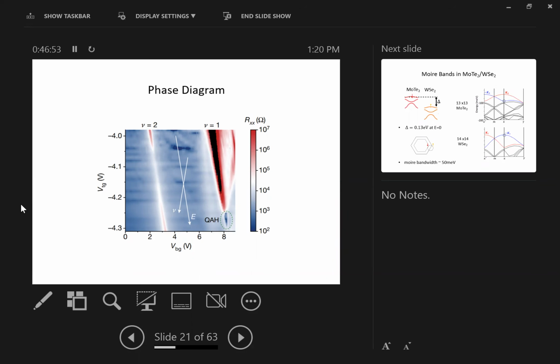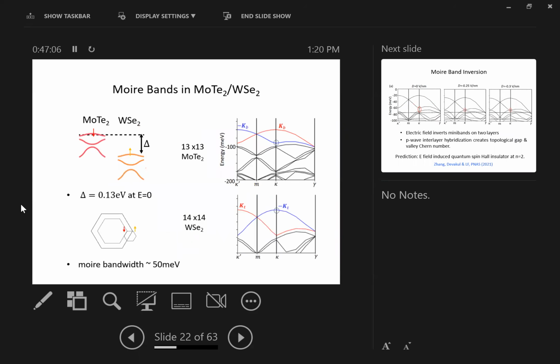Okay, so at filling factor 2, at band insulator, right, we see there's a transition from one kind of band insulator to another kind of band insulator, right? So this already reminds us of this gap closing transition between topological and atomic insulators. And indeed, that's what we found by the DFT calculations on MoTe2 and WSe2. So the 2 layers again have a band offset.